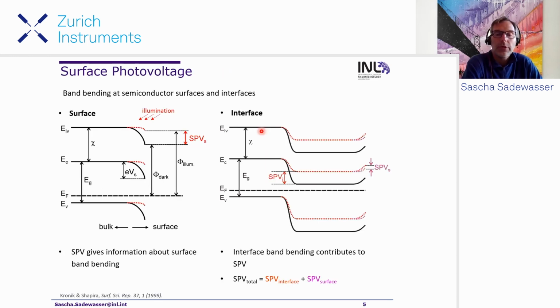Maybe one more word in addition to what the previous speaker said about light. When you have a semiconductor, normally at the surface you find some band bending due to defect states. And when you shine light, these defect states can recharge, and this leads normally to a flattening of the band, and this is observed as the surface photovoltage. If you have a system where you even have an interface or a buried junction, as we also saw before, then both of these, the surface and the interface, can contribute to the surface photovoltage. They can even have opposing effects. So sometimes it might be quite difficult to distinguish between the two. But these are the effects that eventually will lead to the signals we observe as surface photovoltage, and also, of course, as time-resolved surface photovoltage.